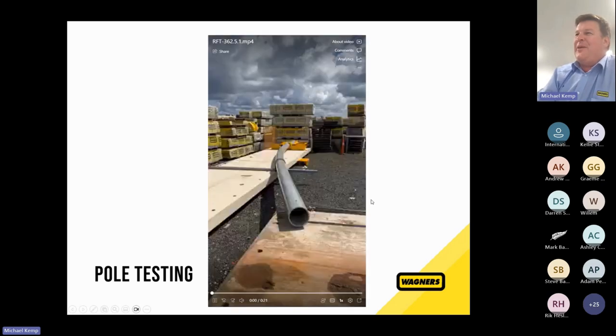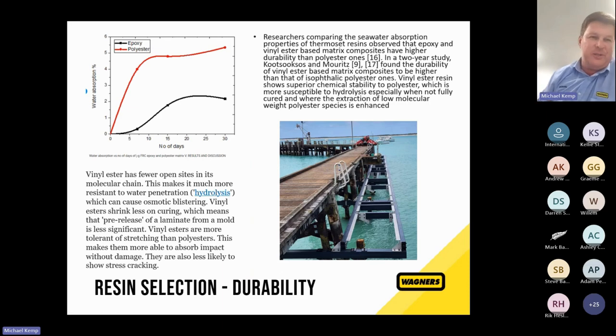So up until that final failure, we could have released the pole, and we would have almost gone up and down the same load deflection curve. You would not have noticed a loss of stiffness. So hopefully that worked and you heard the sounds. But that cracking noise is really an easy indication if you're doing a test of what's going on. With a vinylester resin, you hear it late. With a polyester resin, you're hearing it from maybe 50% of its ultimate capacity.